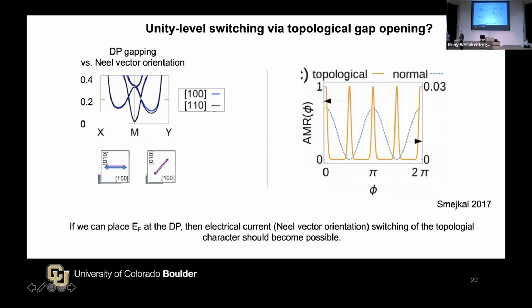Now going to the first part. This may be a long story, but I heard some discussion about possible different magnetism near the surface, and also that magnetic domain walls may contribute to this zero gap mode. Can you tell us briefly what is happening? I am calling it disorder at this time, and domain walls with tiny enough islands. On the other hand, what we really believe is that each layer, when it's away from the surface, is ferromagnetic, and that energy scale is relatively large. But at the surface, the disorder is much more severe. And are there domain walls or whatnot? I'm sure there must be.